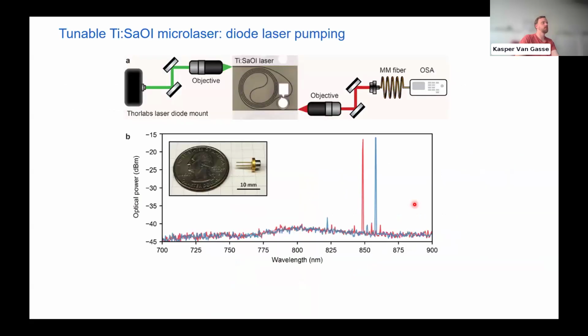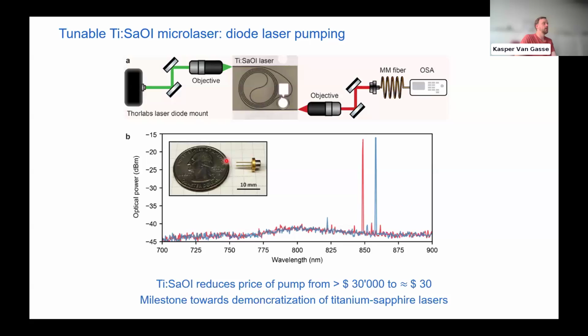And then finally, and maybe most importantly, because we made our titanium sapphire laser so compact and so small, it is now possible to make a tunable titanium sapphire laser and pump it with this very simple TO-CAN diode laser. This costs about $30. So making a fully integrated tunable titanium sapphire laser is really here after many decades of trying. Now you can really do it on chip and achieve the full tuning range. And this effectively makes the cost of the pump section go from more than $30,000 to basically $30. You don't need the chiller, you don't need the tabletop setup.